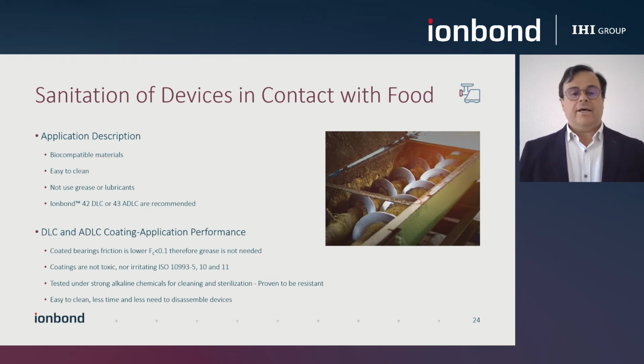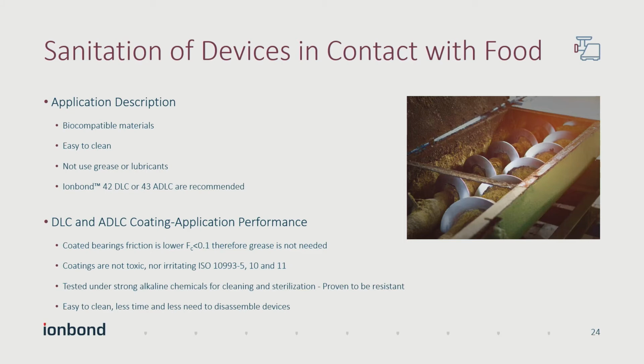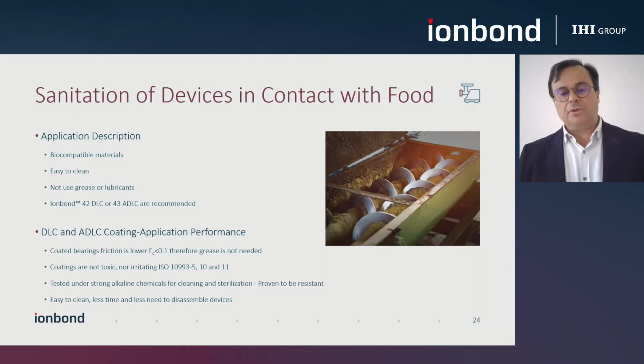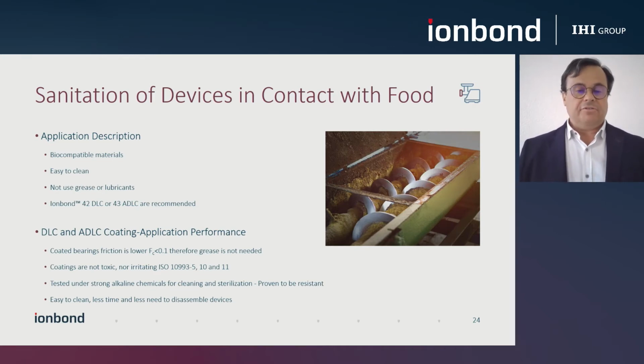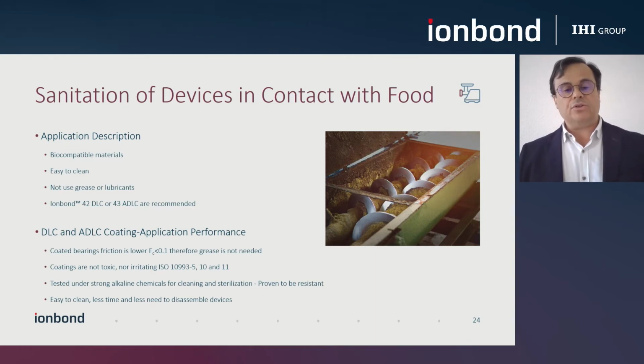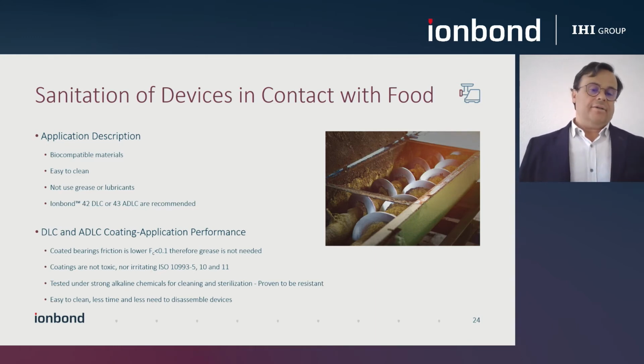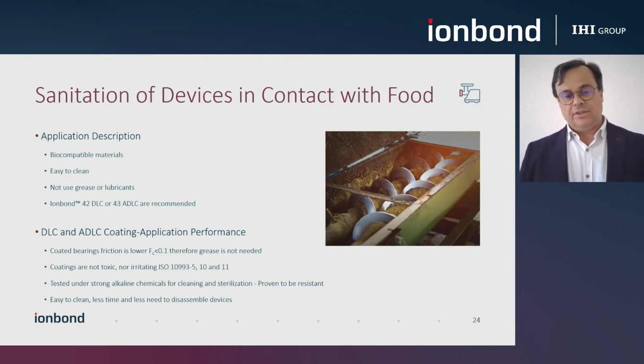We have also tested these coatings against biocompatibility standards ISO 10993, and they have proven to be biocompatible. We have also seen that these coatings are very stable because they really withstand strong alkaline chemicals during cleaning, disinfection, or even sterilization cycles. So by using our coatings, you achieve better sanitation of your system. They become easier to clean and easier to maintain, and you take less time to maintain the system because you need to disassemble the devices less often.